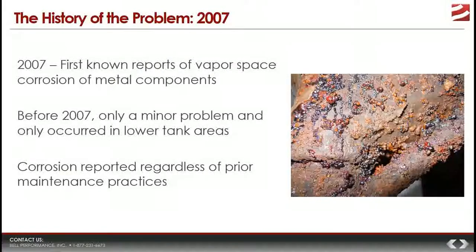If you concurrently increase the proportion of saturates, well, saturates happen to be something that microbes love to feed on and love to metabolize. So now you're increasing those at the same time. So it wasn't just the removal of the sulfur, it was the change in the composition of the fuel around 2007, creating an ultra-low sulfur diesel fuel, which is a lot less resistant to microbes. And thus, you have the potential for serious microbial issues, which a lot of people think is what was contributing to this vapor space corrosion problem.